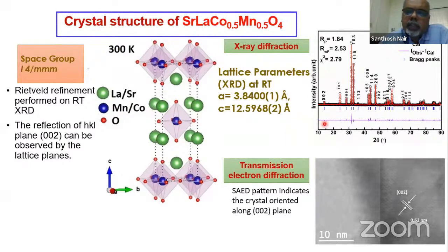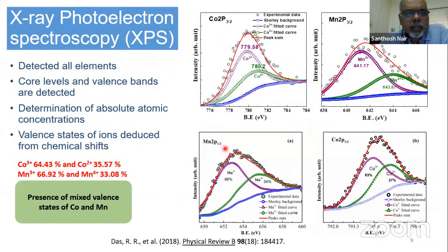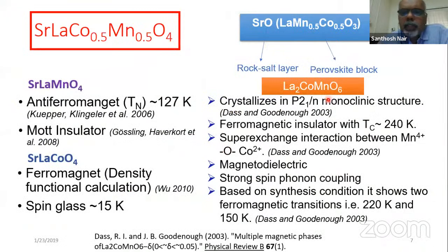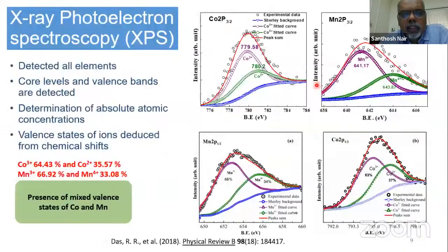That we do by X-ray diffraction followed by a Rietveld analysis. And we are pretty comfortable saying that it's a very good single phase system. Okay. Now, in the parent compound La2CoMnO6, there is a manganese 4+ and cobalt 2+ interaction, which gives them the ferromagnetism. So we want to see whether that ionic state remains the same in our layered system also.